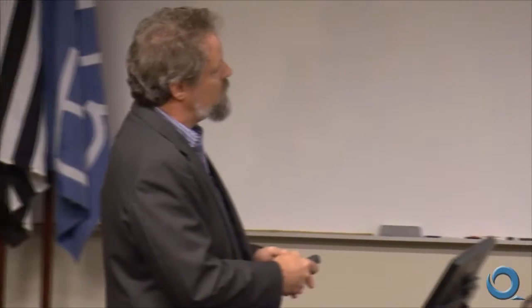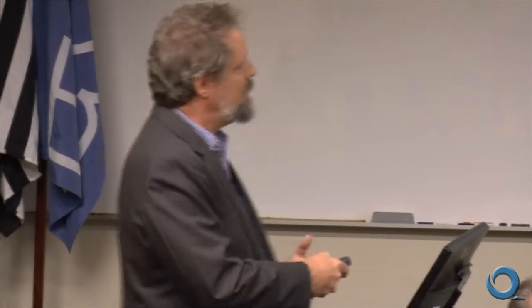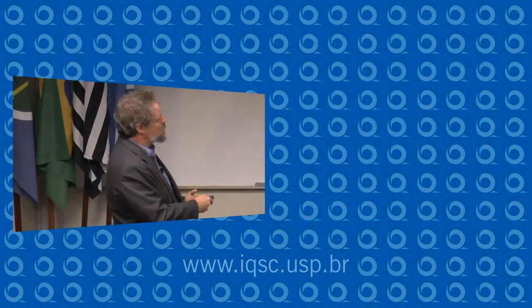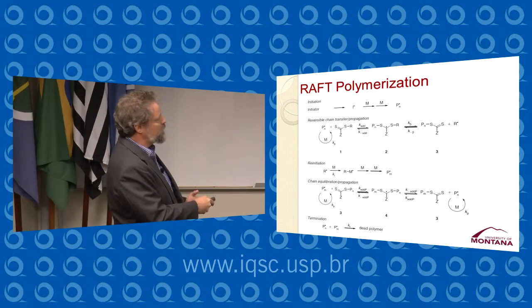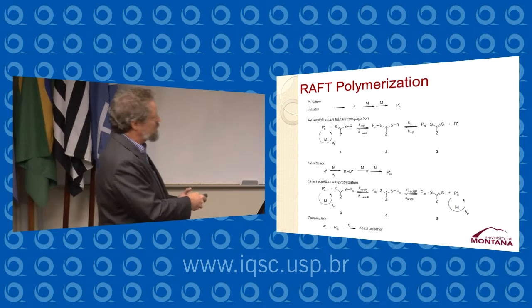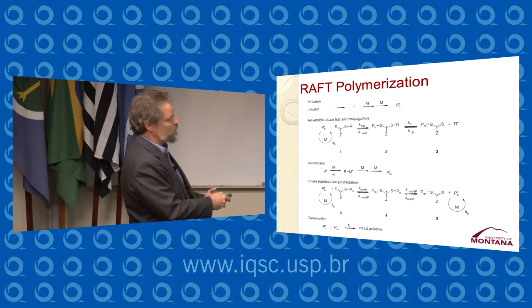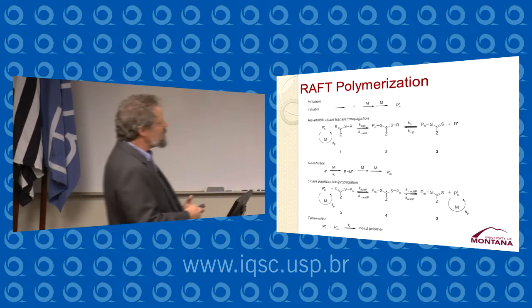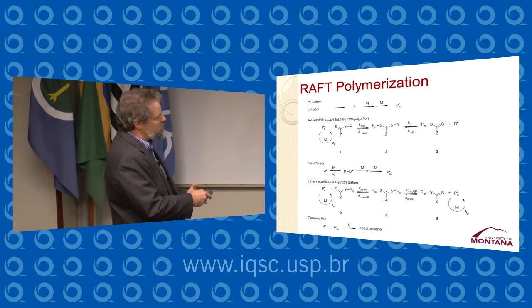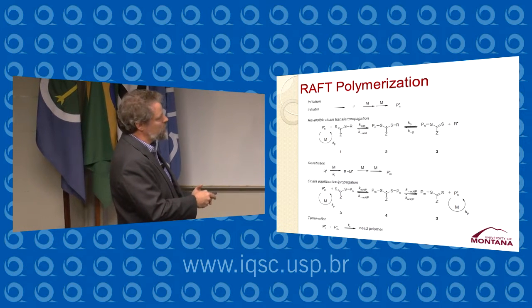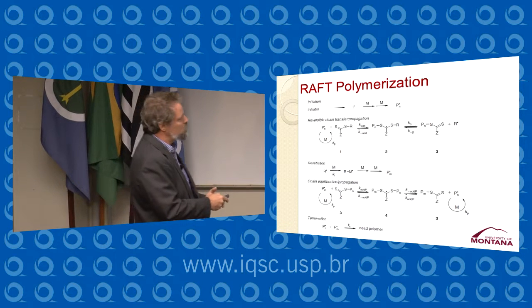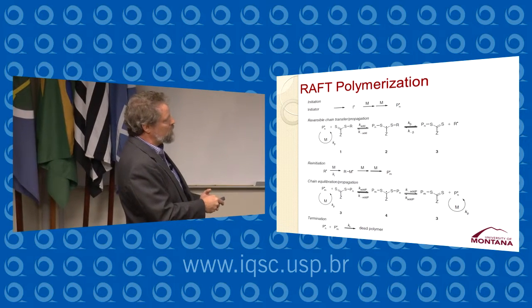So what we're using instead is this controlled technique where we use a chain transfer agent, and this chain transfer agent has a functional group which stabilizes free radicals and also a free radical leaving group on it. So once we initiate the polymerization, one of those growing polymer chains will find the chain transfer agent, react with it to form this intermediate which is stable and unreactive. The concentration of this chain transfer agent is much higher than the concentration of the initiator. So most of the polymer, once it's initiated, is going to end up in this form.